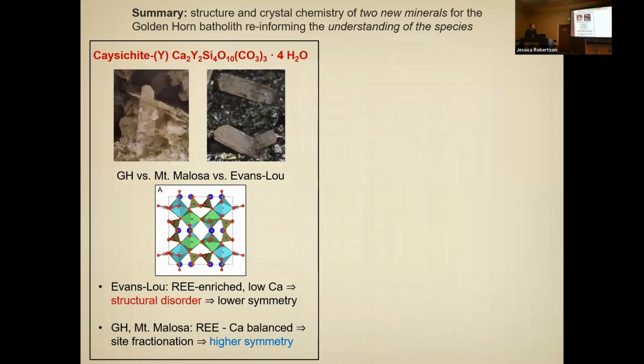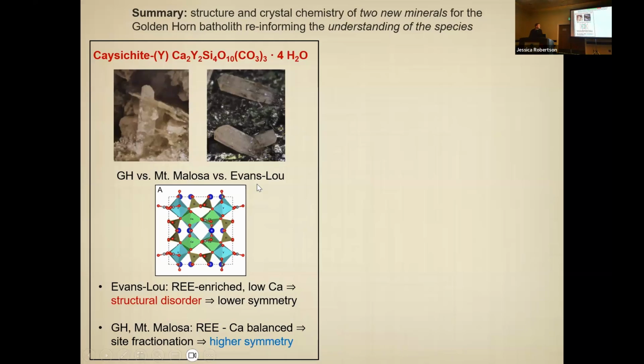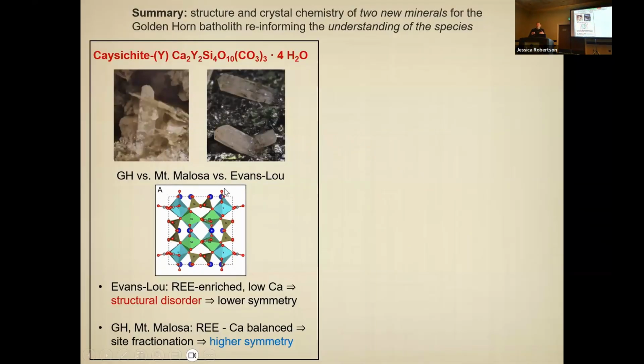So now let me summarize this. Here is what we learned about Caysichite. Again, a new species for Washington Pass, and it could be added to the MinNet database. We compare the Golden Horn to the Mt. Malosa and Evans-Lou type locality, and we would now propose Mt. Malosa to become a co-type locality for this Caysichite because of the higher symmetry. We have this structural disorder which lowered the symmetry in the type material, probably because it grew fairly rapidly, and this is why you have this different crystal habit, this more fibrous growth, whereas here you have these nice orthorhombic crystals.